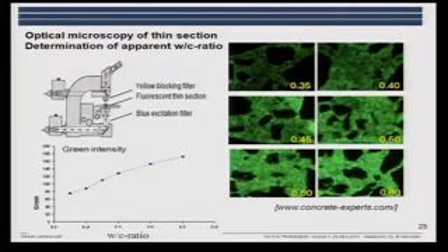But of course, when you're doing this, it's apparent capillary porosity because the samples have to be cured in a similar manner, both temperature and time-wise. If you cure your sample for a longer time, of course you will have an apparent lower capillary porosity.